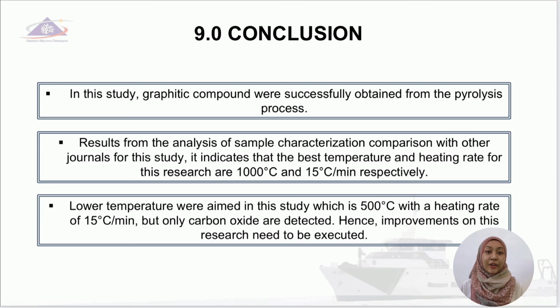To conclude, graphitic compound was successfully obtained from the pyrolysis process. Results from the analysis of chemical characterization indicate that the best temperature and heating rate of this research are 1000 degrees Celsius and 15 degrees Celsius per minute respectively. A lower temperature was aimed for in this study, which is 500 degrees Celsius and a heating rate of 15 degrees Celsius per minute, but only carbon oxides were detected. Hence, improvements on this research need to be executed.